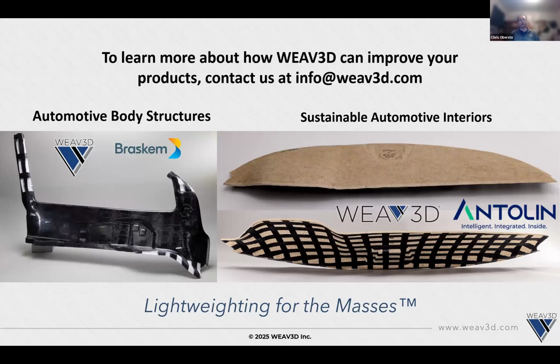With injection molding, it partly comes down to how you gate the part. Edge gating is going to be more aggressive than center gating or other types of through thickness injection. But usually we are relying on tooling features in the tool to pin or tension the lattice during the forming process. Also, in certain geometries, if there's not a lot of complexity, you might actually prefer not to heat the lattice in order to keep it more intact during the injection process. Because of how thin these lattices are, the injection molding step very quickly heats up the polymer on the surface. So you don't really have to get the lattice hot in order to get good adhesion, but you're more doing that to get it to drape or conform to the tool if you need a complex shape to be produced.